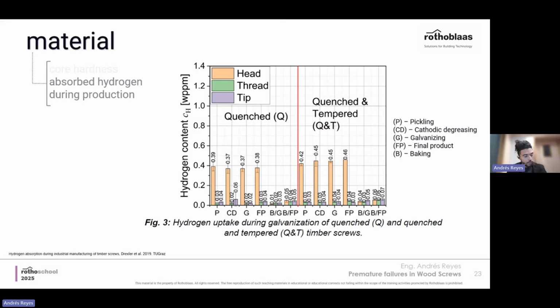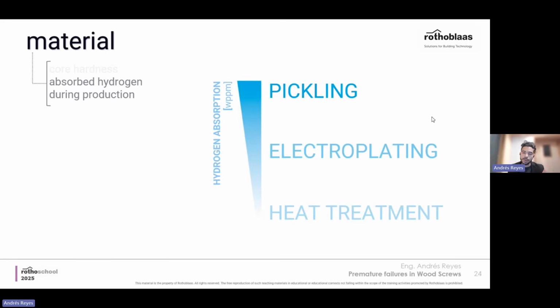Where can hydrogen get inside the material of our fastener? This is from research by Graz University, and they measured the hydrogen inside the screw after every production process. You don't need to know every process, but some of them have more or less influence. More or less, we can summarize it: the pickling process, which is an intermediate phase between the cold forming and the electroplating process, is the one where hydrogen absorption is influenced the most. Then the electroplating itself can also add hydrogen, and finally the heat treatment process can also induce some hydrogen, but a lot less. Let's say we put those three main phases of the process in order of most to least important.